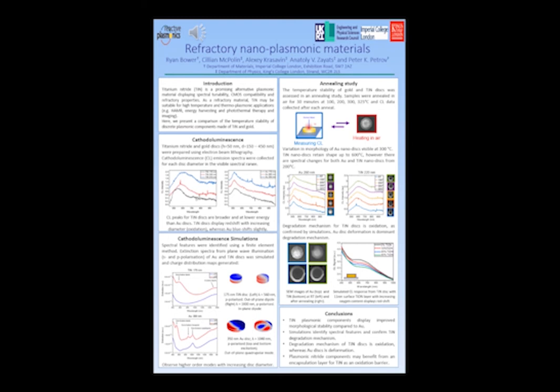And this allows us to observe excited plasmon modes within the discs. We can then identify these modes using simulations, and we see here that the dominant mode in the visible spectral range for both titanium nitride and gold is an out-of-plane dipole mode. We also see that titanium nitride has peaks that are lower energy and broader when compared to gold, and this agrees with the data that we collected experimentally. We also note the evolution of higher order modes as disk size increases, and we can observe this as well in the gold nanodiscs of 350 nanometer diameter.